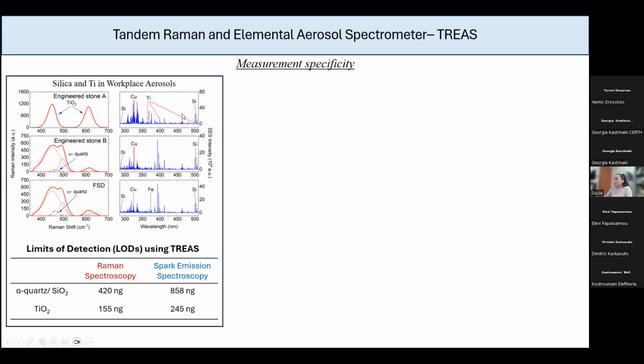Something else that we see in the elemental identification is silicon, which we do not see in Raman, and this is probably because we expect this peak at 465, and it's probably covered by the presence of titanium dioxide. This shows why we need both measurements, where one technique can see one compound that the other cannot see for any reason. In the next two cases, we see only crystalline silica, which is alpha quartz, that we can see through Raman spectroscopy. And then again, using spark-emission spectroscopy, we can see the element as well.